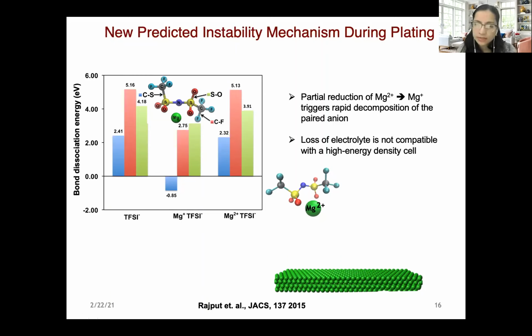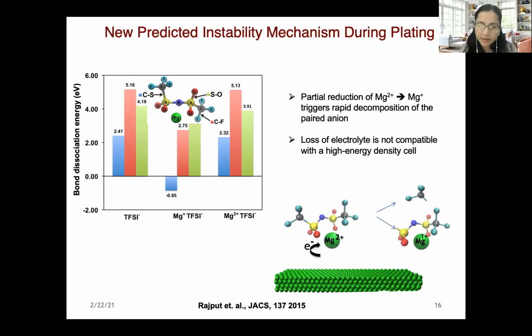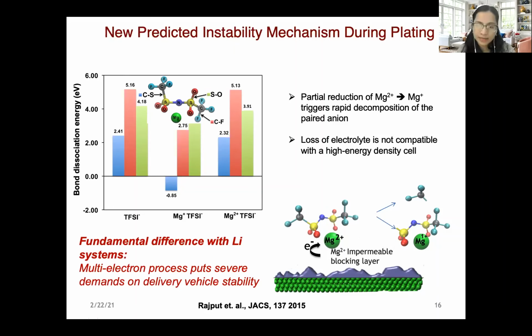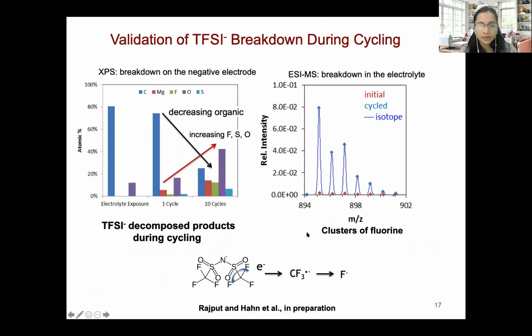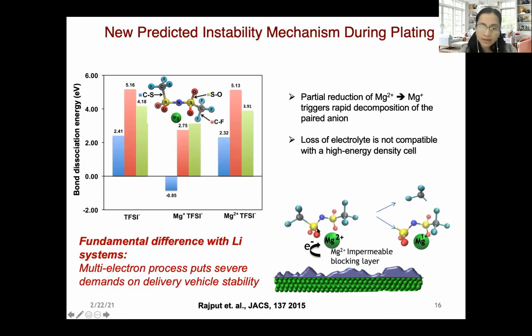So what's happening here is that during the charge transfer process, this ion pair undergoes a partial reduction by taking an electron possibly from the electrode, and this process activates the anion and makes it susceptible to decomposition. And that's pretty bad for our battery because we are not just losing the active species, but we are also depositing a layer of this decomposed product from the anions, which forms this blocking layer and does not allow conduction of magnesium ions. So this fundamental difference between lithium and magnesium, this multi-electron process, puts a severe penalty on the stability of delivery vehicles here, which in this case are the anions and not the solvent molecules.